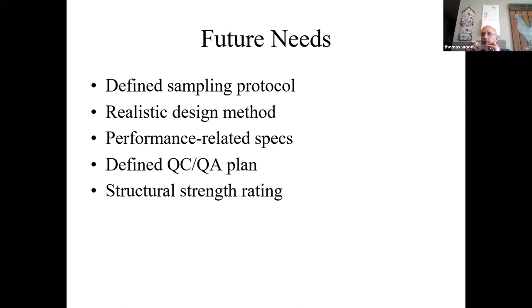You're going to be able to rejuvenate the old binder, and recompact it to where it should be equal structurally to the strength that it was when it was first paved. We're not there yet, but we're getting a lot closer. The rejuvenators that people are working on to allow them to use more RAP through a hot mix plant, they're making some real good headway, and I see it coming over to the cold side of the business. And when we get there,